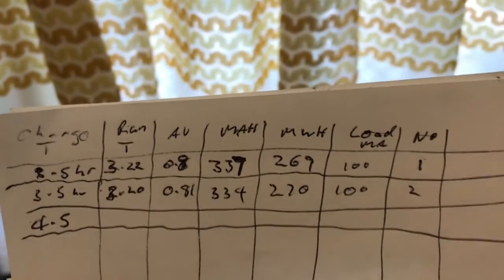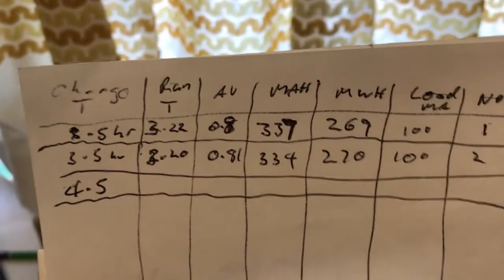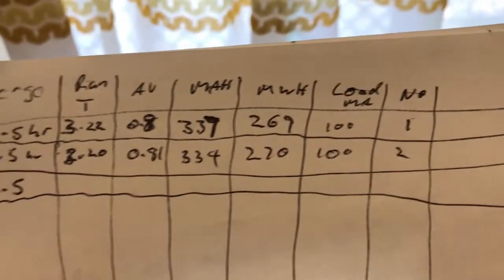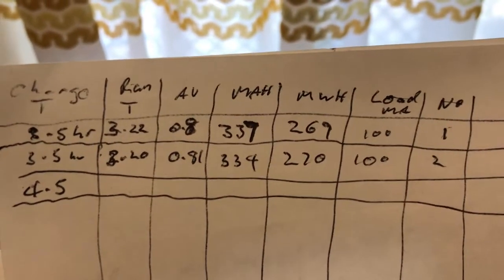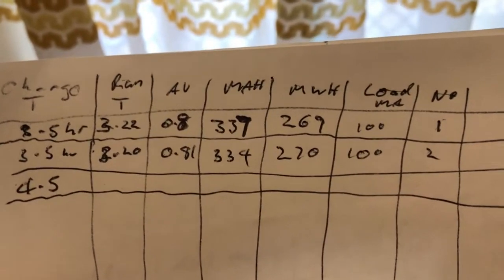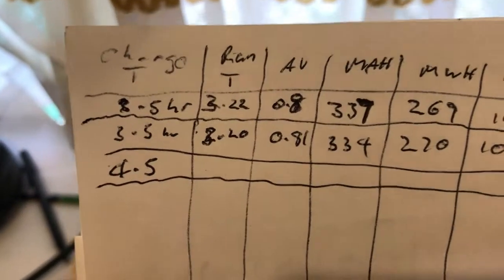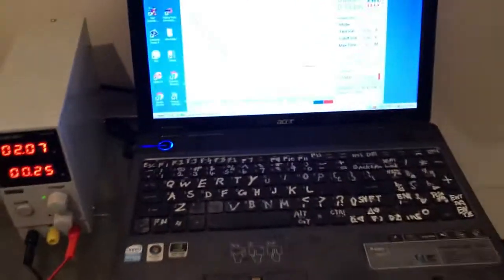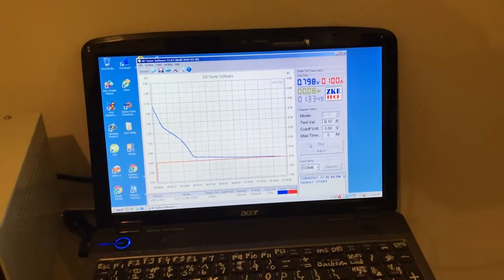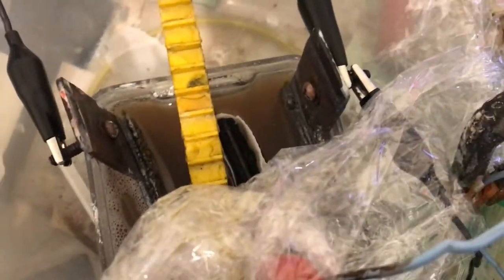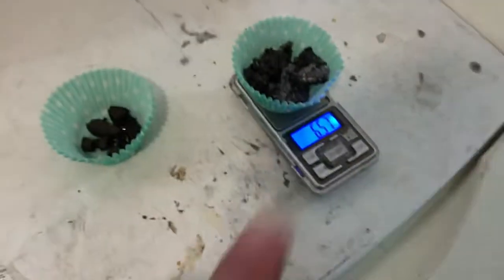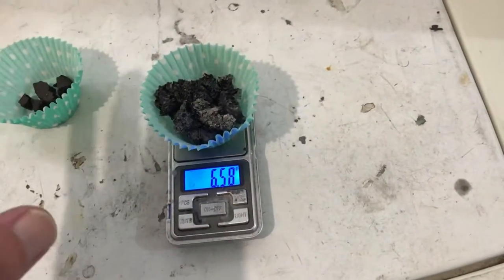This one's still running. This is the third charge, not including the two on the video already. So it's around about the same. 337, 334 milliamp hours, and today it had a 4.5 hour charge, and holding lower voltage though, but it's still going good. There's no cell discoloration. And we're going to back the binder off to 2 grams for 10 grams of carbon.